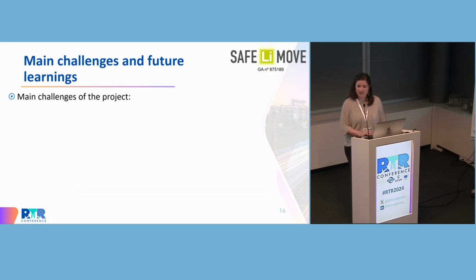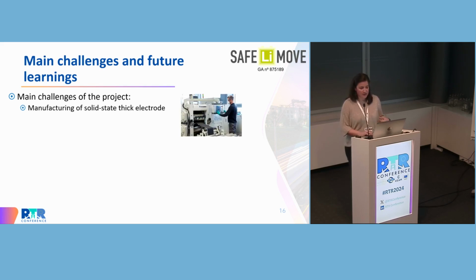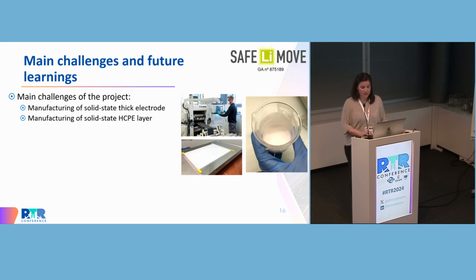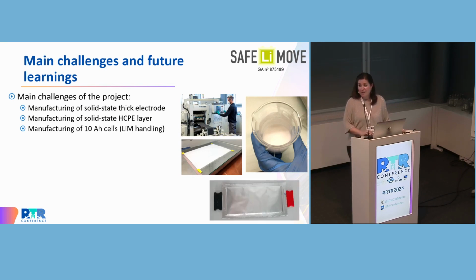And then I wanted to highlight the main challenges of the project, because it's not only about saying what is the outcome, also what we have faced during these years and the learning that we are taking out from here. And I will say that the most challenging part, of course, at material level, there are many things that we can do at lab scale for meeting KPIs related to, for example, ionic conductivity, thermal stability, anodic stability. But then we need to consider how this is going to be scaled up. And these are the main challenges that we have faced related to the manufacturing of the thick solid-state electrode, the manufacturing of the hybrid ceramic polymer electrolyte layer, and the manufacturing of the 10 ampere-hour cells, 3 ampere-hour cells at the end, mainly because of the lithium metal handling without any type of current collector.